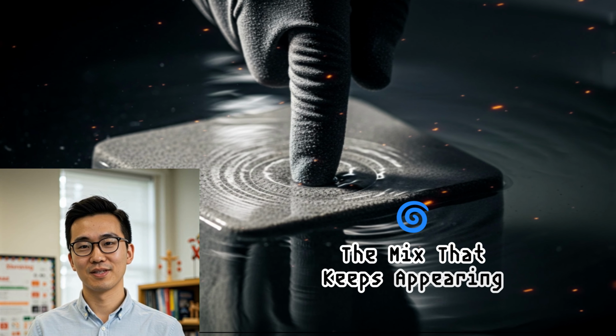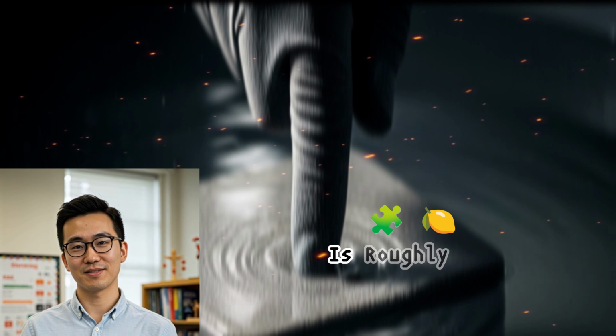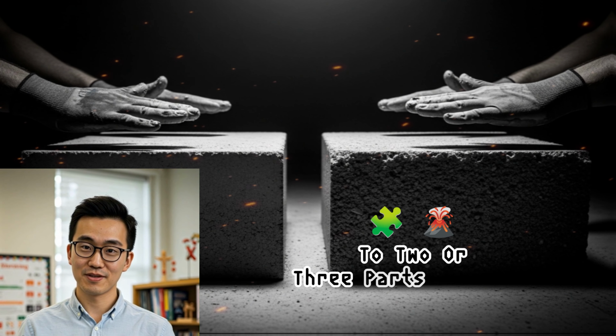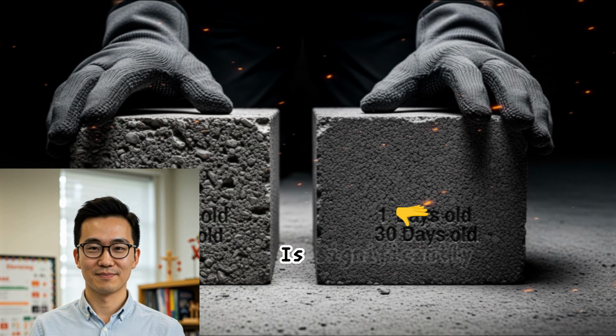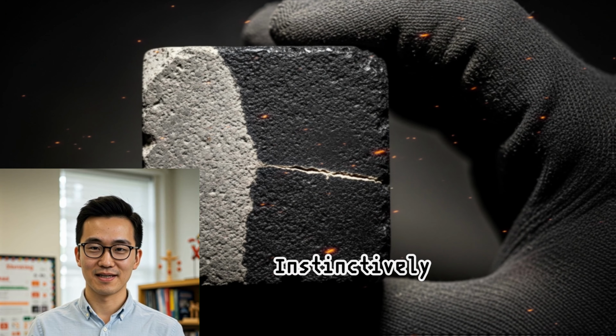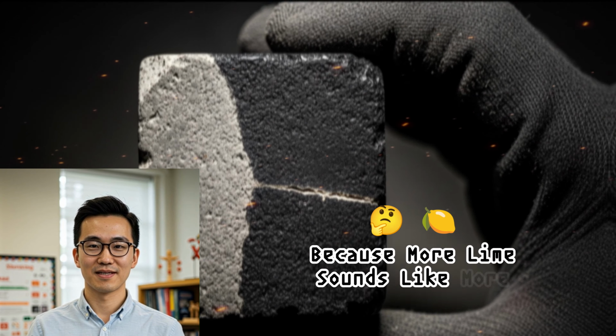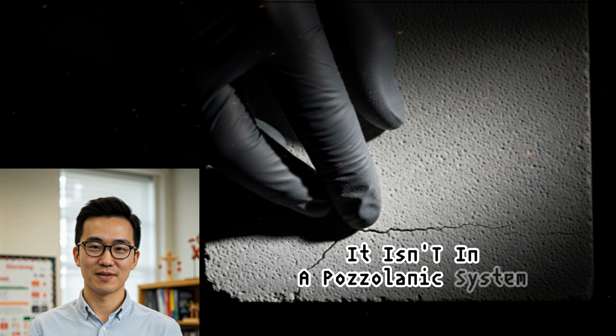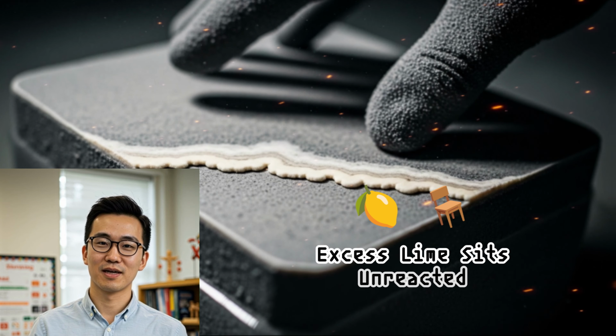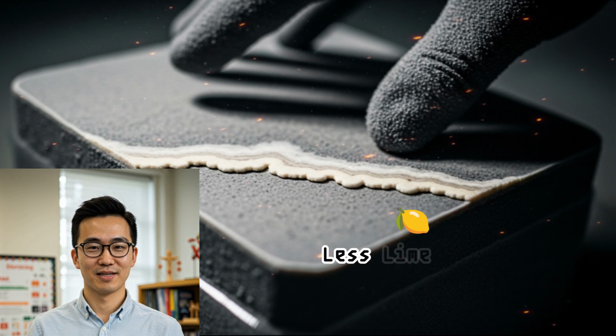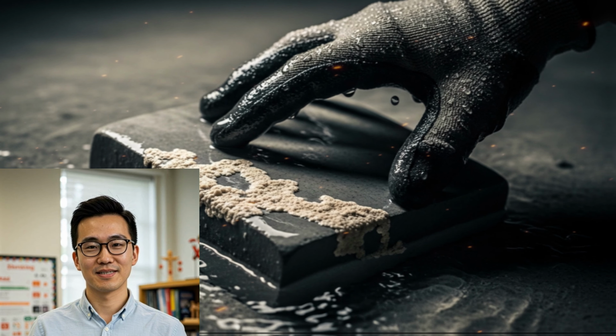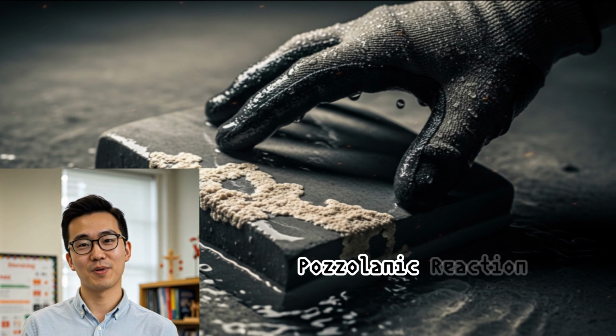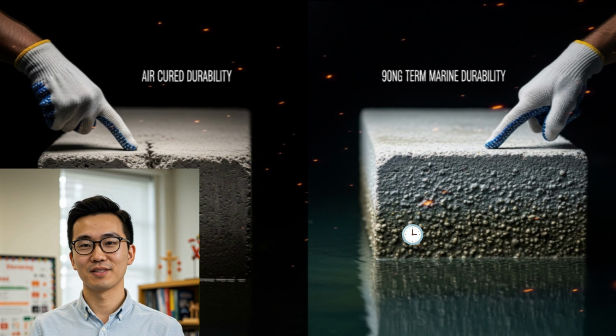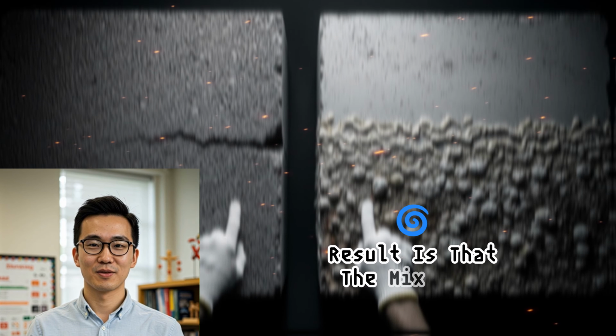The mix that keeps appearing in analysis of actual Roman structures is roughly 1 part lime to 2 or 3 parts volcanic ash by volume. Sometimes even less lime than that. The lime content is significantly lower than what modern builders instinctively reach for, because more lime sounds like more strength. It isn't. In a pozzolanic system, excess lime sits unreacted, waiting to be leached out by water. Less lime means more ash relative to binder, more surface area for the slow pozzolanic reaction, more tobermorite formation over time. The counterintuitive result is that the mix that looks weaker on day 1 is stronger at year 100.